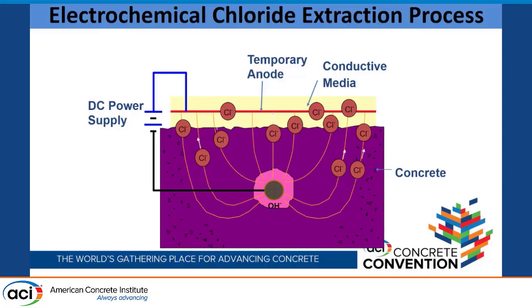Not all the chlorides are removed, and that's probably one of the problems with this process is the name. Yes, chlorides are reduced, but it's really more of a corrosion mitigation process than it is a chloride extraction process, so that's a little bit misleading, and you definitely develop a higher pH zone around the rebar as a result of that.